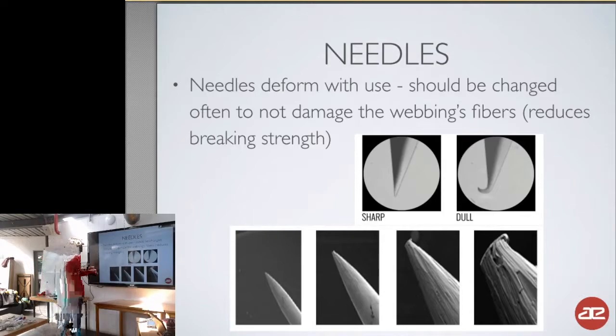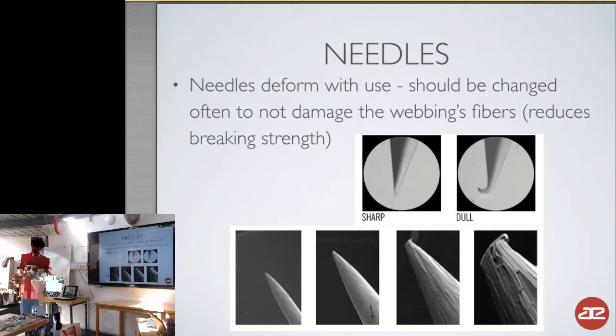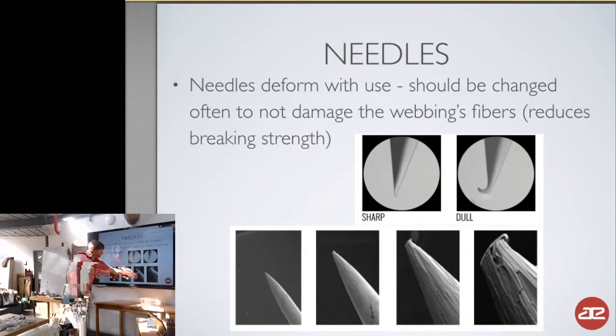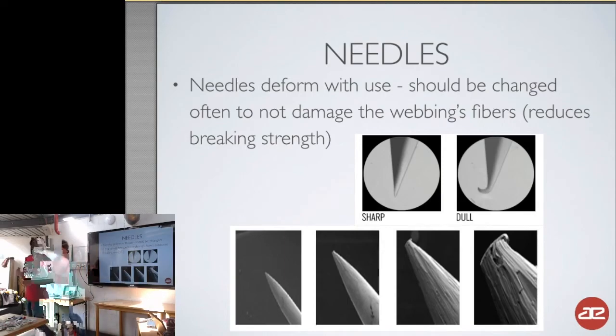And the same goes for needles that are not obviously dull, but are just worn out. You can see some microscope pictures down here. If the needle was used too often or for too long, the surface of the needle becomes quite rough, and this also destroys the fiber structure of the webbings. So what you want from somebody who sews your webbing is that he changes the needles quite often to guarantee the maximum strength for your webbings.